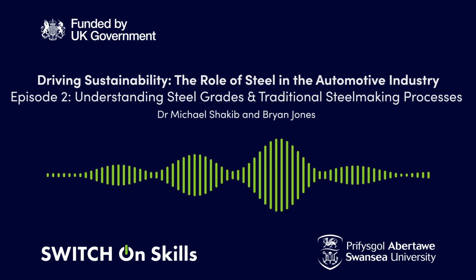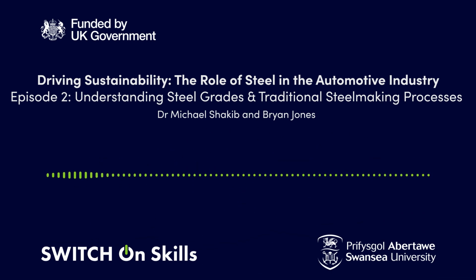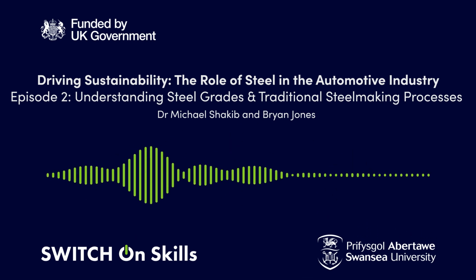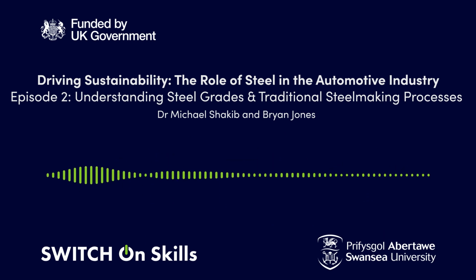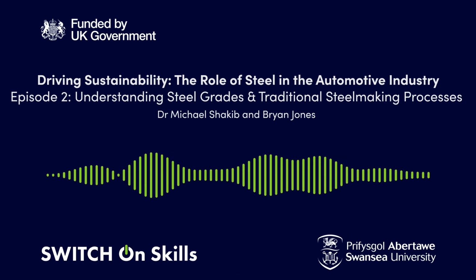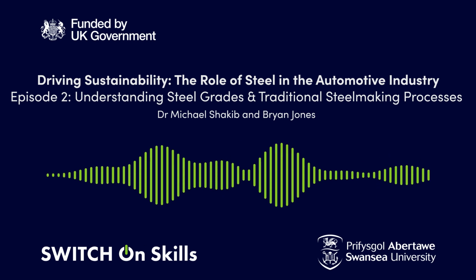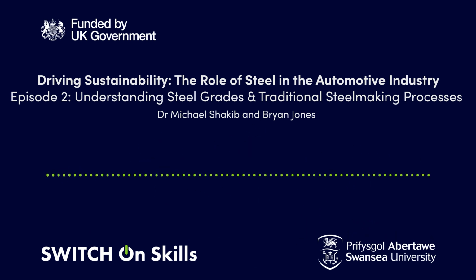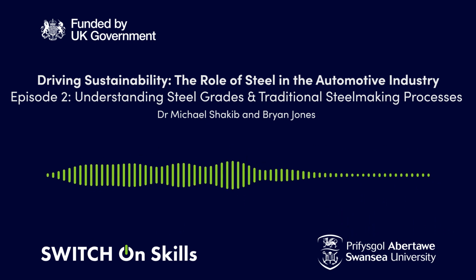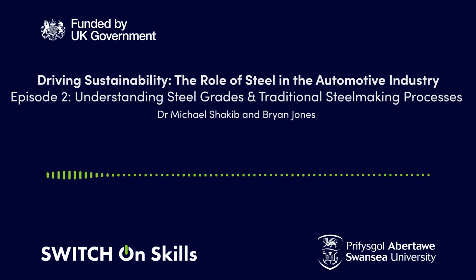Yeah. And then the third primary cooling program that's adopted is to produce the dual phase steel. In this case, again, you're cooling down to the ferrite nose. You'll always need ferrite for formability. That's the soft stuff, yeah. So you're cooling it down into the ferrite nose, hold it there for a limited period of time until you've got as much ferrite as you want, and then you quench it. And when you quench that product, you end up with a microstructure that's far more disorganized, far more irregular in shape. A martensite microstructure, which, as I mentioned earlier, is a very hard grade of material, which imparts significant strengthening to the product.